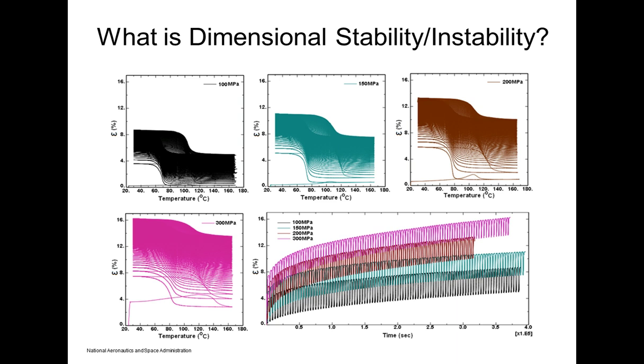Now, with a spring, the issue comes in that I'm no longer in a homogeneous field of stress or strain. And so in that case, I have a much harder time determining what is the level of strain in my component that I need to reach in order to get to stabilization. And again, we come back to that process where we say, if there's a way to link that stabilization strain that's happening in my component to that, then I'll know the intended deformation field and extension that I need to go through in order to produce that level of stabilizing strain in the component. And that's something that the person just has to find a connection to themselves, because it really is the underlying strain state within the component that produces the stabilization. Not as trivial to do in a complex multi-axial problem like a spring, but it can be done.